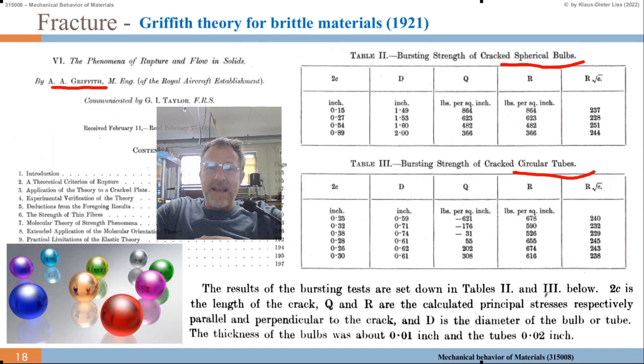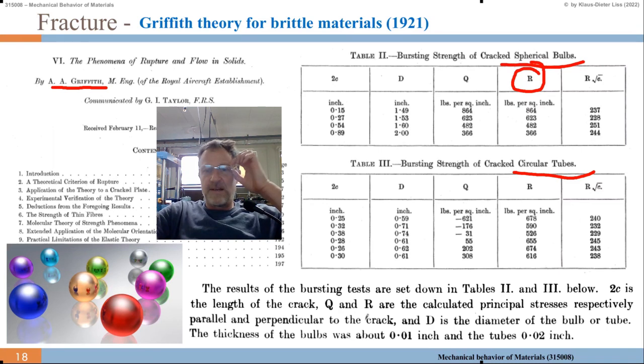2c is the length of the crack. Q and R are the calculated principal stresses, perpendicular and parallel to the crack. Q is parallel to the crack, and R, which is what we're interested in, the higher one, is perpendicular to the crack. D is the diameter of the bulb, tube, cylinder, or sphere.